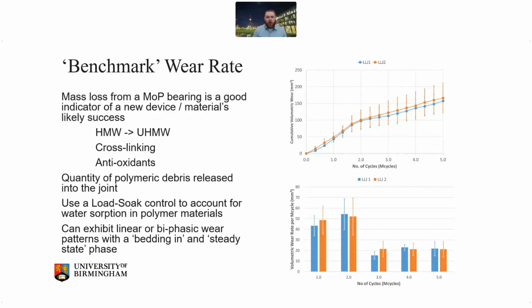But ultimately, the goal here is to quantify that release of polymer debris. And what you end up with is basically running these tests, which for a 5 million cycle test, will often take 3 months to just run the test, not to mention any kind of development or fixture development that needs to be done. And you end up with a fairly basic wear rate at the end of the test.